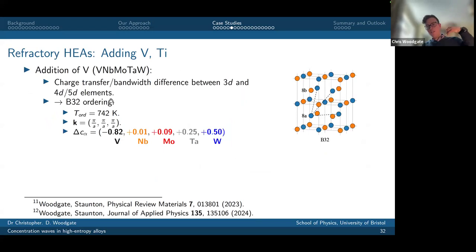If I add vanadium to make this 5-component alloy, what some people call the Senkov alloy, what I find is that there's this interesting phenomenon where, because vanadium is a 3D element, the atoms are a little bit smaller, they have a narrower bandwidth. There's charge transfer from the large elements to vanadium, and there's also this bandwidth difference. Vanadium has a narrower 3D band compared to the 4D and 5D bands. And what I find there is that instead of getting a B2 ordering, I actually get a B32 ordering, okay? So the ordering temperature is a little bit increased, 742 Kelvin is the Landau theory estimate. The wave vector now, the minimum eigenvalue, if you like, is occurring at the P point, which is pi over a, pi over a, pi over a. And that describes this B32 ordered structure here.